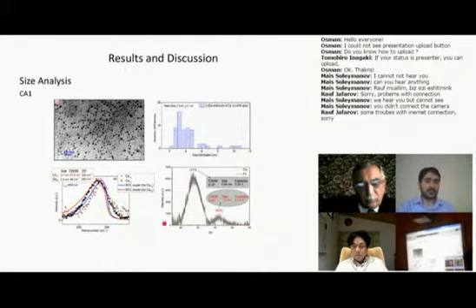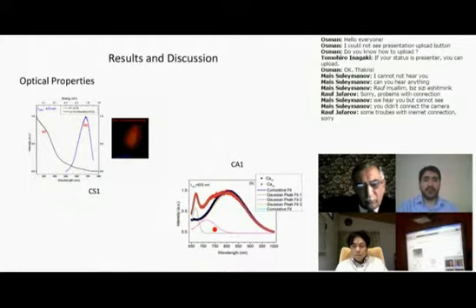And also I took another Raman spectra to understand what it actually is. It's also another asymmetric peak. This here is the XRD peak of the XRD spectra of our particles. Also, it suggests that germanium is in the core.